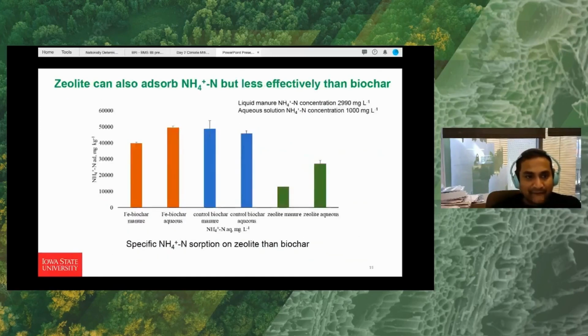Next slide, please. Zeolite can also absorb ammonium nitrogen, but less effectively than biochar. So in this study, we did iron biochar, control biochar, and the zeolite for the ammonium nitrogen, and we have shown that the iron biochar is absorbing more ammonium from the aqueous solution than from the manure, whereas for the control biochar, there is no significant difference, and the zeolite can absorb ammonium but less compared to biochar. It absorbs more ammonium from the aqueous solution than from the manure.